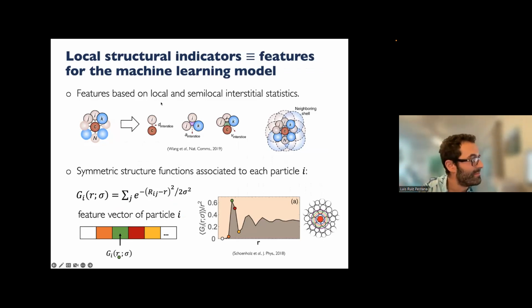So these numbers could be the distance between that particle and the nearest neighbors. You can measure interstice areas between 3 particles. You can measure interstice volumes. You can measure those with the nearest neighbors. You can measure those with the second nearest neighbors. You can calculate a lot of these simple metrics. And this could be exactly what those local structural indicators mean.